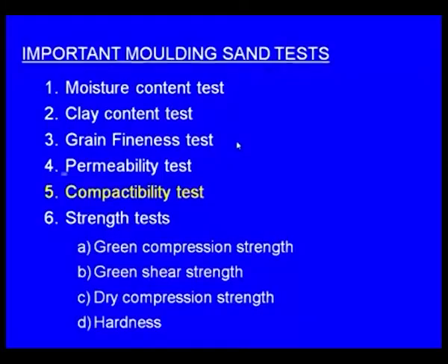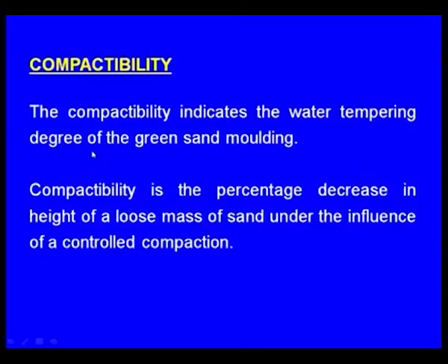Next one, let us see the compactability test. So we have covered moisture content test, clay content test, grain fineness test, permeability test, and now let us see the compactability test. What is this compactability? The compactability indicates the water tempering degree of the green sand molding. Then how to measure it? Compactability is the percentage decrease in height of a loose mass of sand under the influence of a controlled compaction.